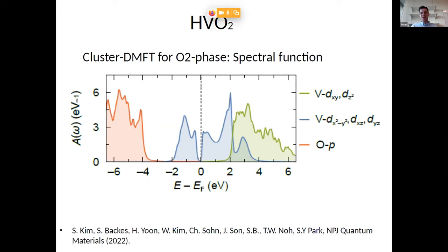Yes, in some sense. My question was aiming at the fact that I understand the validity of the intersite potential approximation in pure VO2 when there is only one electron which only occupies this bonding antibonding state. But then in this hydrogenated picture, you now have additional electrons. So isn't there a reason for also including the intersite effect on the other orbitals, except for this A1G? Well, but those really do point in orthogonal directions. So physically, it looks pretty safe to assume that they are not really coming in. Of course, one can always use the hammer and then show that it comes out to be small. But I think we really know that they point away from the dangerous direction. So in that sense, this was not our first priority.